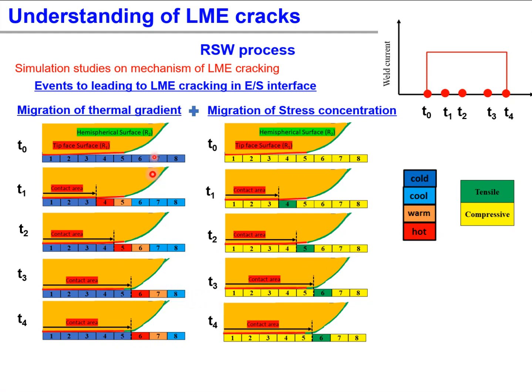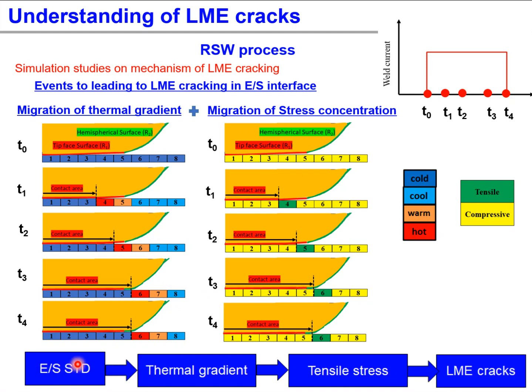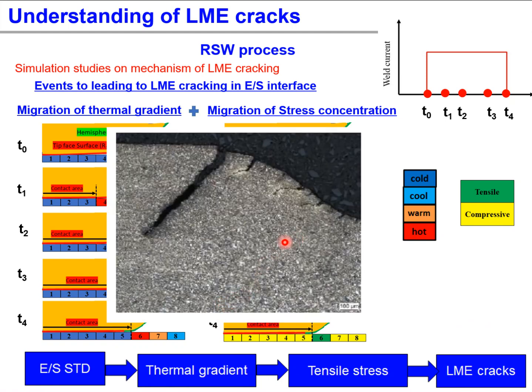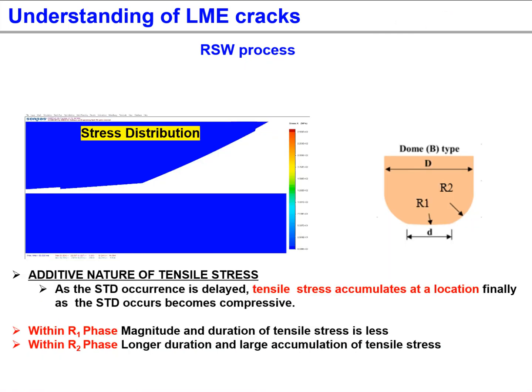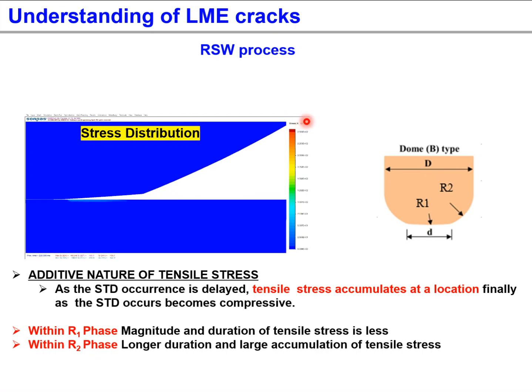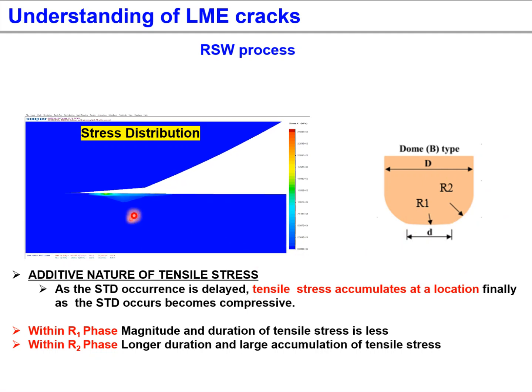With increase in welding time, these four steps of electrode-to-sheet contact, sudden temperature drop, thermal gradient, then tensile stresses, and LME cracks occur toward the outer boundaries. These four steps of the LME cracking mechanism well explain the LME cracks in different locations. However, there is a question of why different crack lengths are observed in different regions of the electrode-to-sheet interfaces. To answer the question, we need to observe the stress distribution in conjunction with the transition of electrode radius from R1 to R2. Within the R1 phase magnitude, the duration of the tensile stress is relatively short.